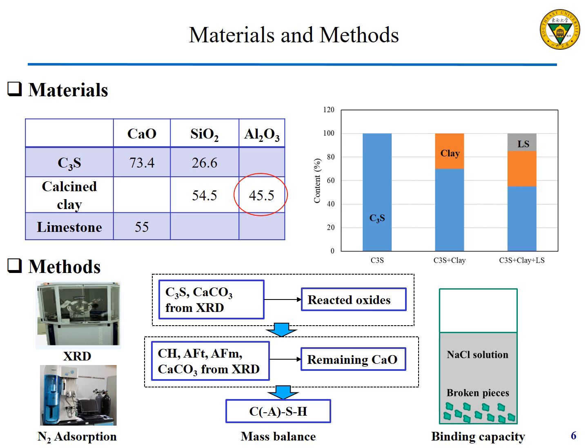For the chloride binding capacity, we use the equilibrium method, which means a few grams of particles are put in different concentrations of sodium chloride solutions. After 2 to 3 months, the relationship between bound chloride and free chloride is investigated.